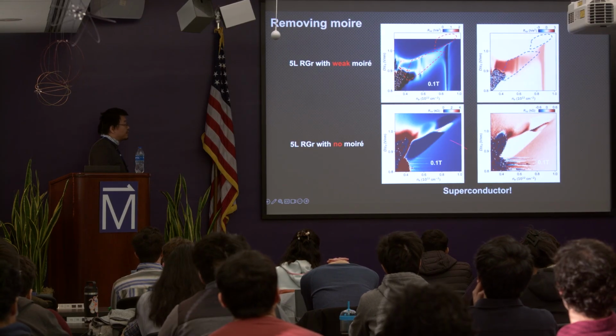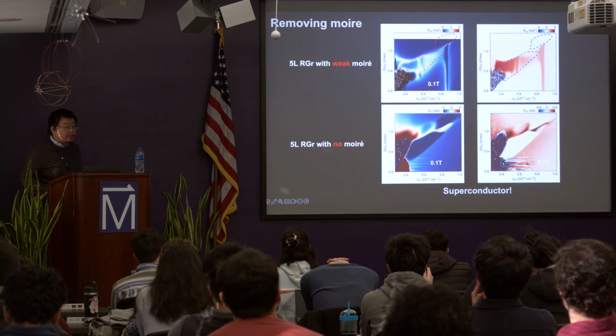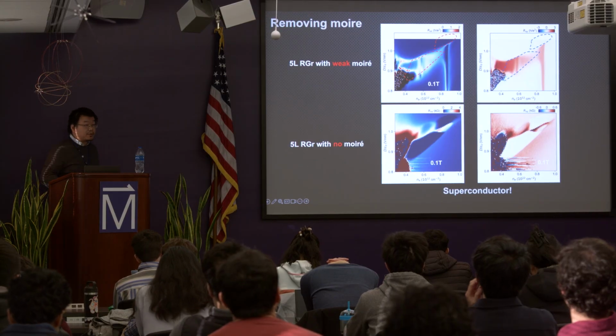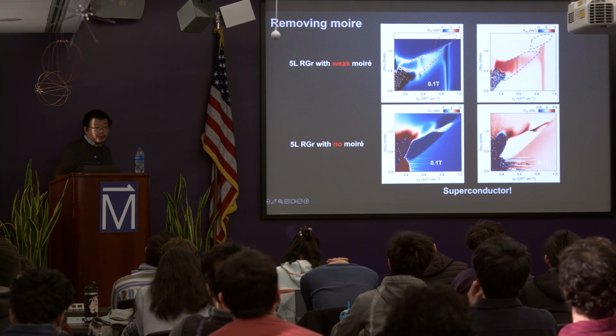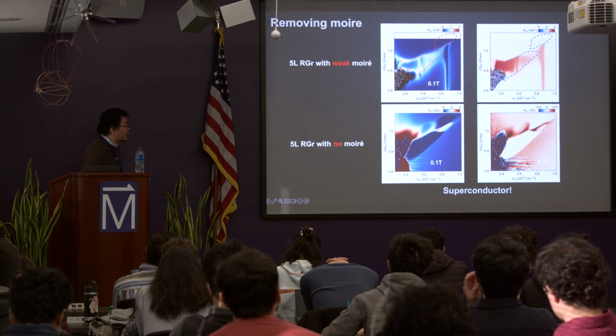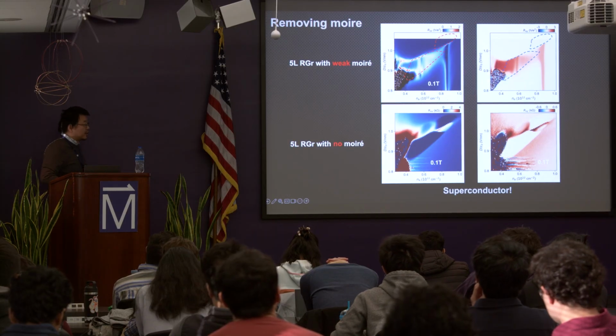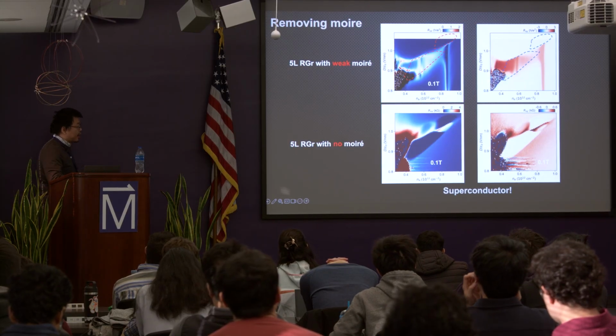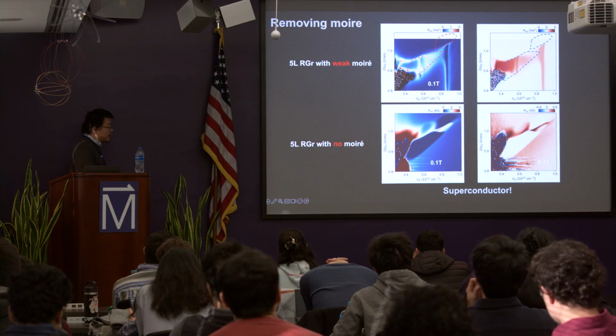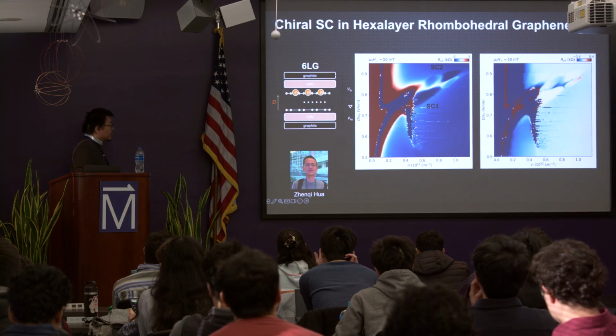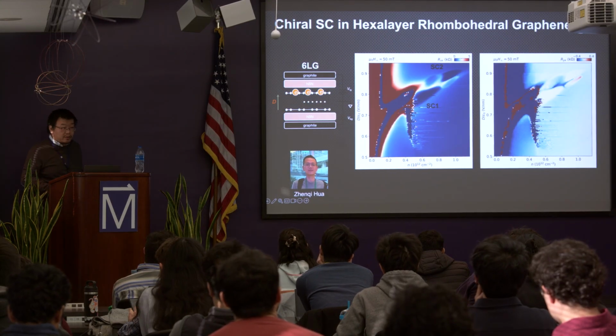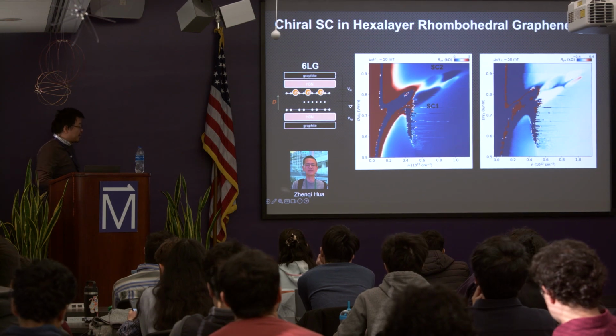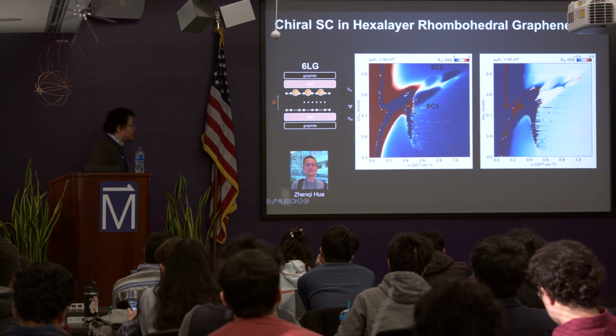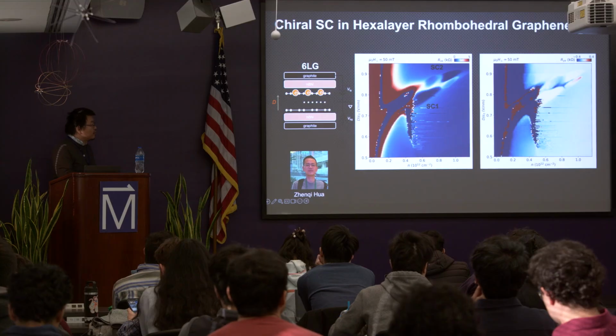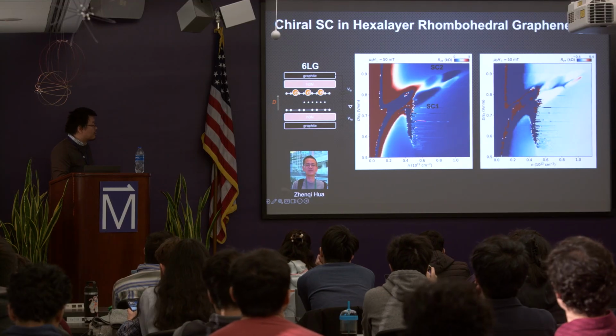And the whole effect is actually very generic. So it's not limited to 5-layer rhombohedral graphene. You can see it in 4-layer, you can see it in 6-layer. And there is actually more interesting stuff compared to what we have already seen. For example, in 6-layer rhombohedral graphene, which is very fresh data we just got, you have a very similar phase diagram.